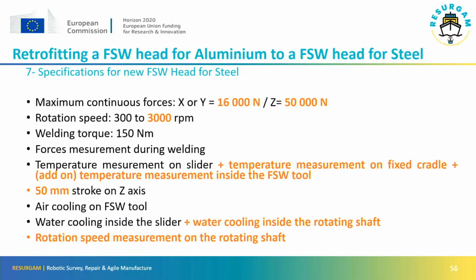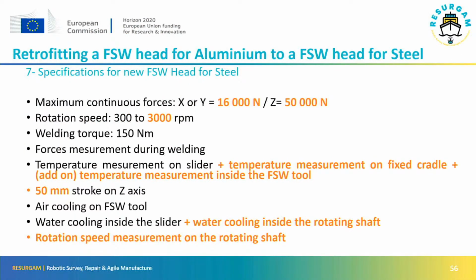Of course, we will keep the force measurement during the welding, and we will have other temperature measurements all around the product, because the main challenge here is the temperature to weld steel is much higher than aluminum, so we need to prevent any damage on the FSW head. So there will be a measurement on the slider as on the first product, but also on the fixed cradle, and we developed an add-on that could be mounted on the head, so we can measure the temperature directly inside the FSW tool. The stroke will be also increased on the Z-axis up to 50 millimeters.